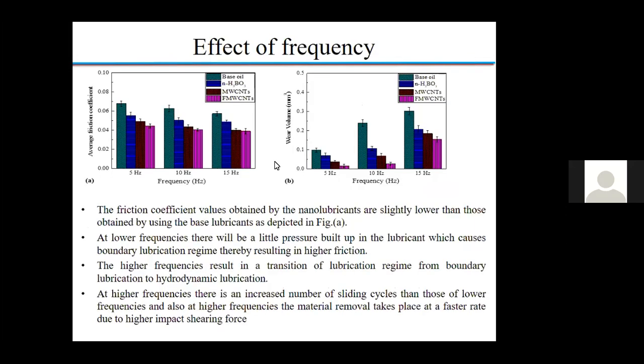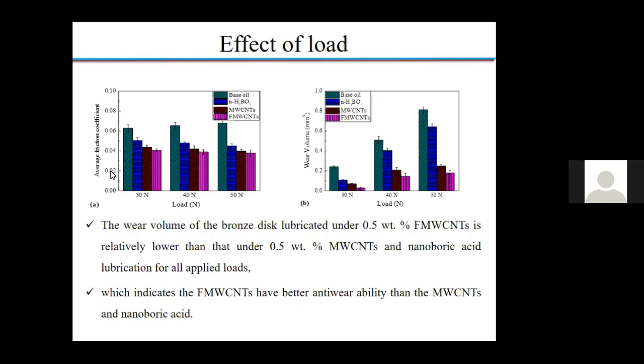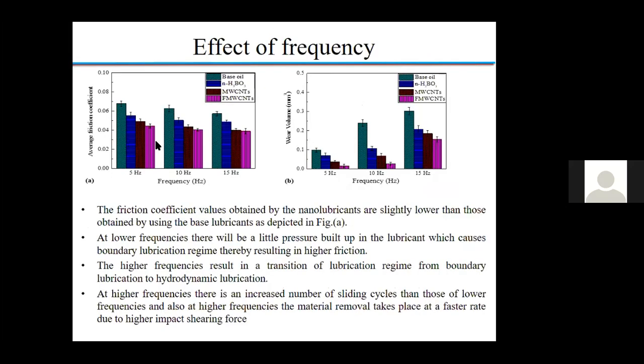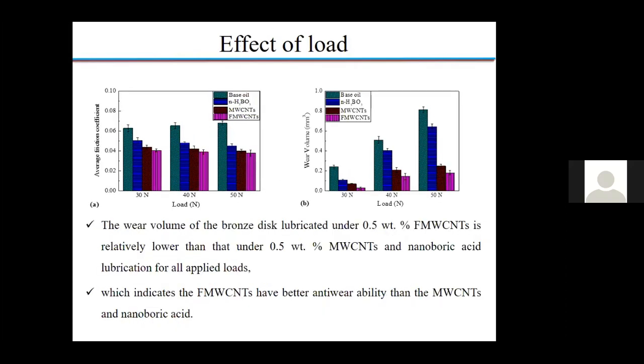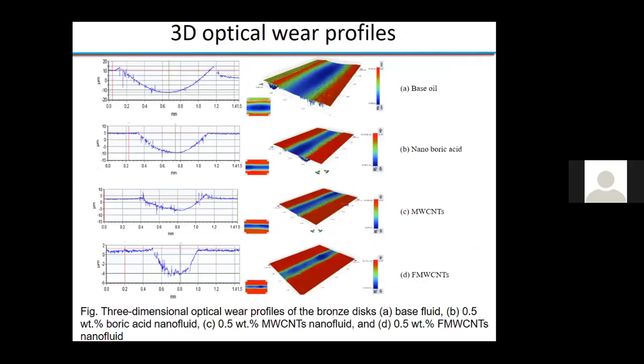Okay, then this is friction and wear volume parameters plotted with respect to increase in load. Here the friction and wear parameters have been plotted with respect to increase in speed, 5 hertz to 15 hertz. So in both cases, there is a significant reduction in wear and friction coefficient for functionalized multi-wall carbon nanotubes. Okay, so these are the results for various loads and speed operating conditions.